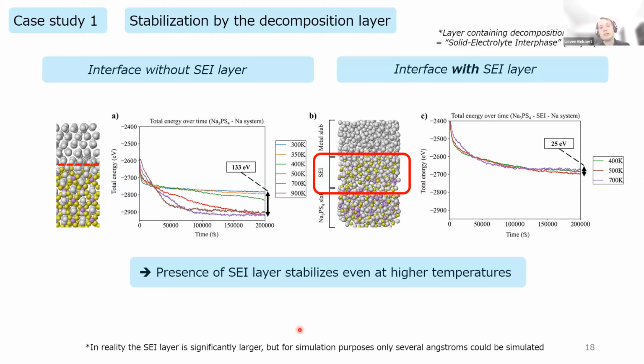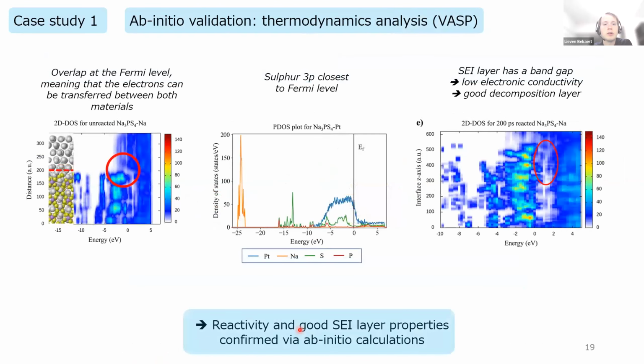Now, so far I've shown you Matlantis results, but what's important is that you can also link it to other techniques to validate it. And one of the first techniques that we used is an ab initio technique. So we used VASP to analyze this system. As you can see in this density of states plot, on the vertical axis you have once again the coordinates, so the depth into the model. On top, you have sodium metal. Below, you have the solid state electrolyte. And you can very nicely see that at the Fermi energy level, you have an overlap. So electrons have the same energy at the Fermi level, meaning that these electrons from the solid state electrolyte and sodium metal can interact with each other and therefore react. So thermodynamically confirming that there is a reactivity between both materials.